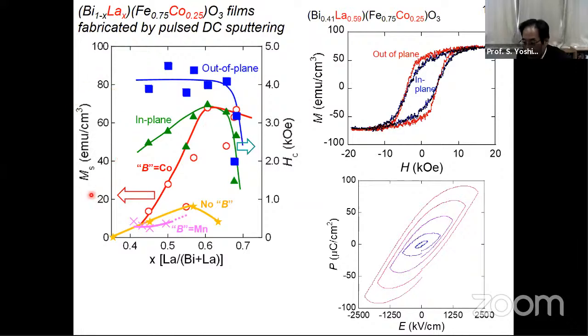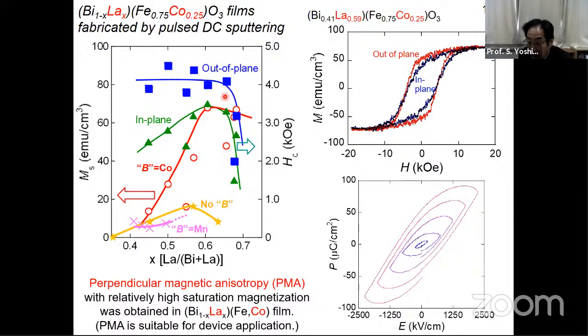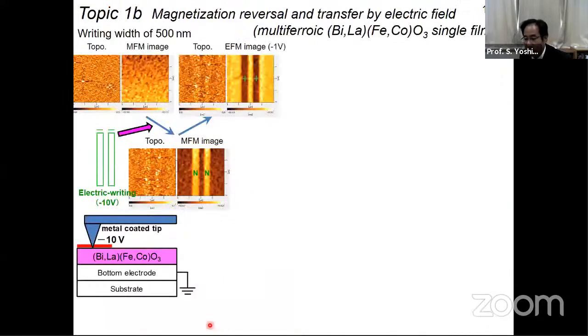Red one is magnetization, and blue one is the other. Out of plane coercivity is larger than in plane, like this. This one is a hysteresis loop of this material. Coercivity and remanence of the magnetization are larger in the out of plane case compared with in plane. So perpendicular anisotropy with relatively high saturation magnetization was obtained in this material. This perpendicular anisotropy is very important for device application.